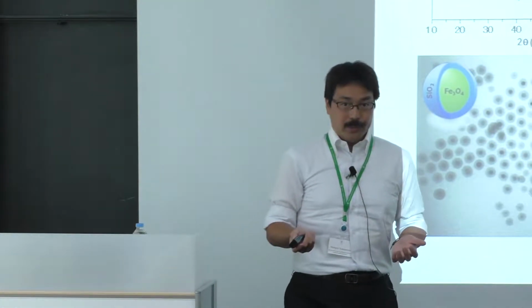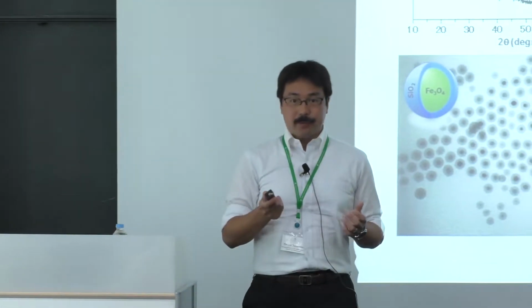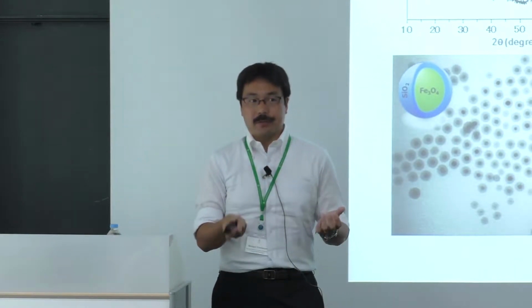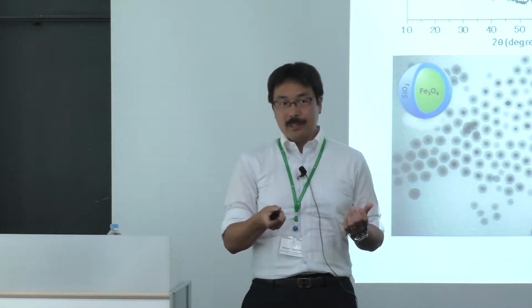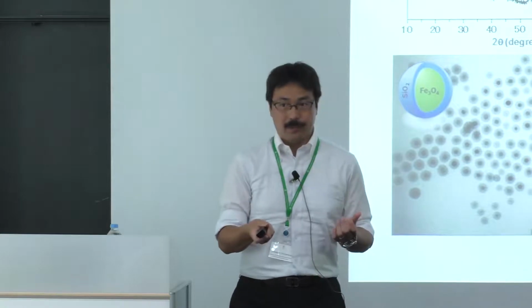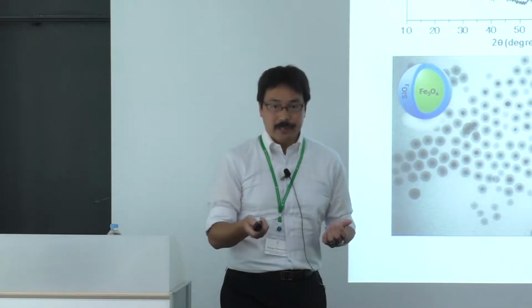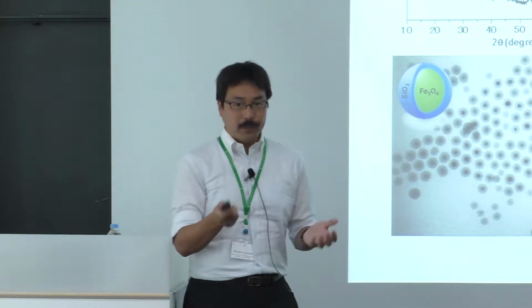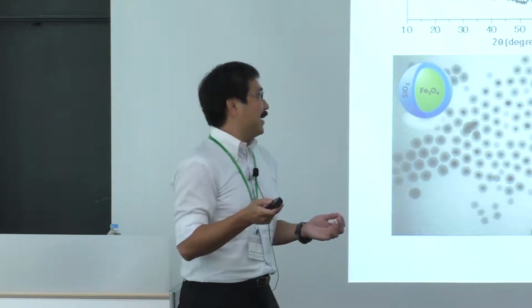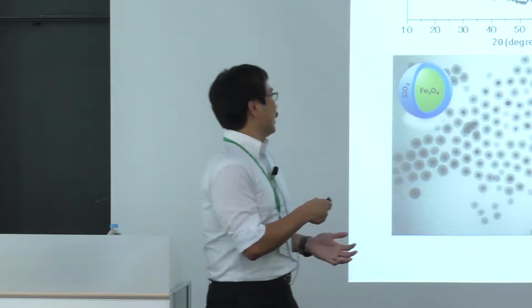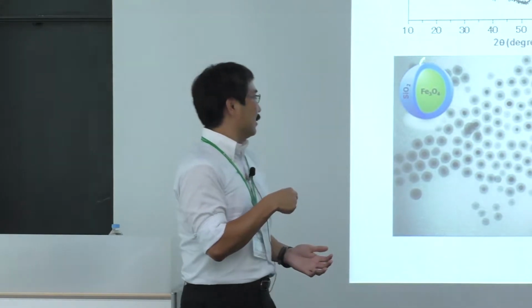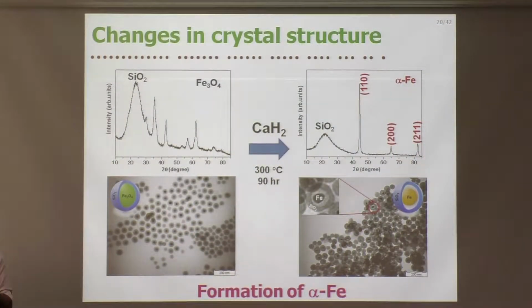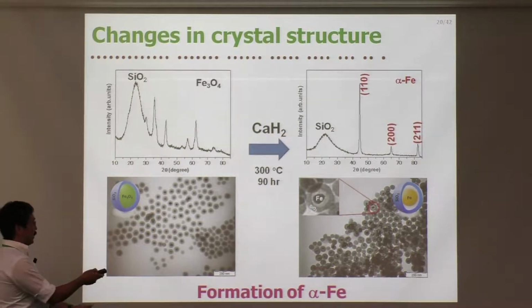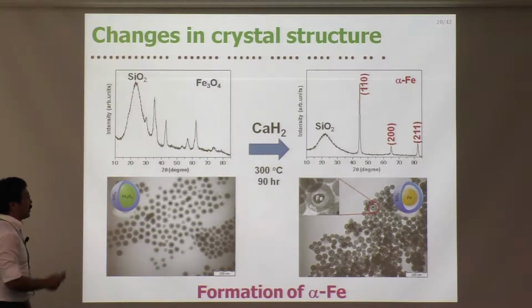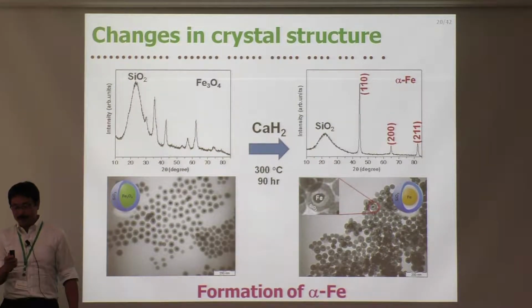Why does the void form? Because we carried out a reduction reaction, which is a reaction that removes oxygen atoms. Since we carried out reduction of the core nanoparticles, during the reduction the starting iron oxide nanoparticles lost their oxygen atoms, so volume shrinkage takes place. Now we see the void. This is a very interesting feature of our reaction.